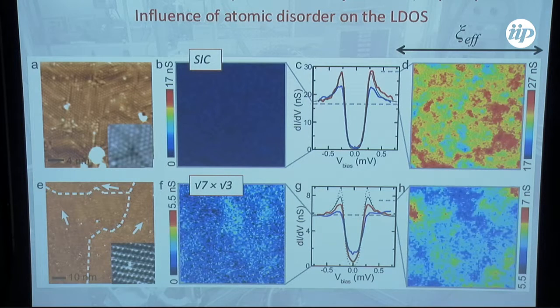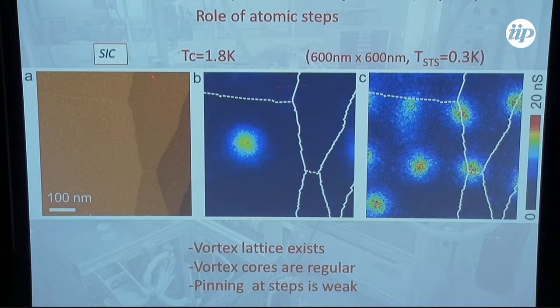So we asked the question if it is really superconducting or something else, because the existence of a gap is not a proof of superconductivity. So we put a magnetic field. Yes, and this is the case of this striped incommensurate material, which is very dense. You see here individual atomic steps of this material, and they are reported here. Then you put a magnetic field, you see one vortex, and then you raise the magnetic field, you see several vortices. Some of them are pinned on the steps, but nothing specific. You can see this situation even in thicker films. Okay, so this material is certainly in a coherent superconducting state because you have vortices, which is a proof of the phase coherence. Okay, and the steps do not play any significant role.